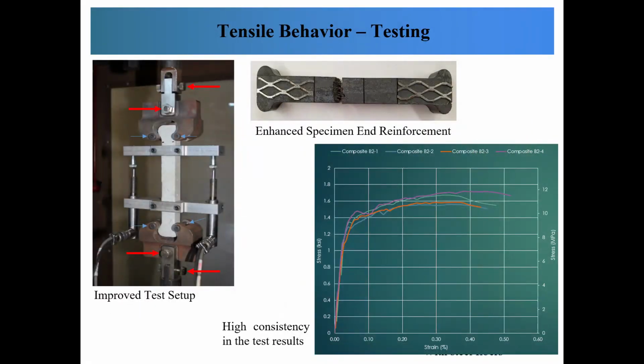For direct tensile testing, dog bone-shaped specimens were used with embedded mesh reinforcement at the ends. Here, the embedded end reinforcement has been placed on the failed specimen to illustrate the location of the mesh. The test setup has been significantly improved to provide rotational freedom to the specimens, see pointed arrows, as well as reliable deformation measurement. As a result, the displayed test results show high consistency and quality, which is usually challenging to obtain.